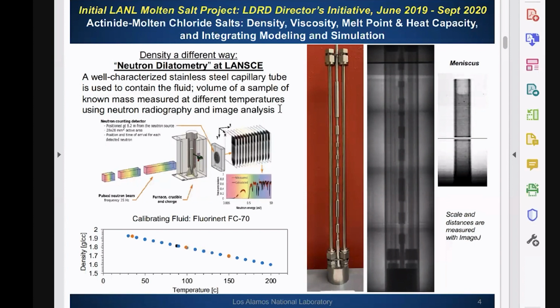So in this density work, we're using what we're calling neutron dilatometry. So this is basically a well-characterized stainless steel capillary tube, and I'm showing a photo of two of them in this assembly right here on the left and right, that's used to contain the fluid. And then what you're doing is you're measuring the volume of a sample of known mass at different temperatures using neutron radiography and image analysis. And so in this graphic here, basically you have the neutron beam focused on the sample that's held within the steel container. So we're taking advantage of the neutron's power to penetrate and image through the big furnace that's holding the sample molten. The detector is seated behind the furnace there. And this graphic is actually showing dynamic radiography, where you have a pulsed beam and lots of different images, and we actually use that for our viscosity measurements, which I'll show in a little bit. But here, for density, we just use static pictures.